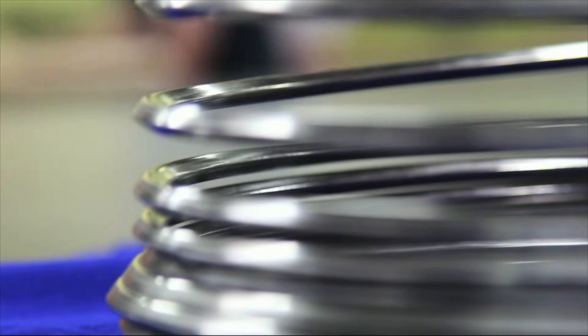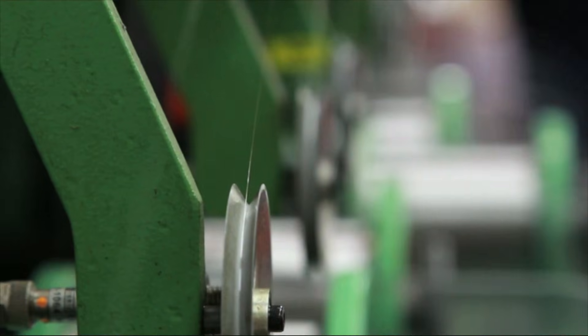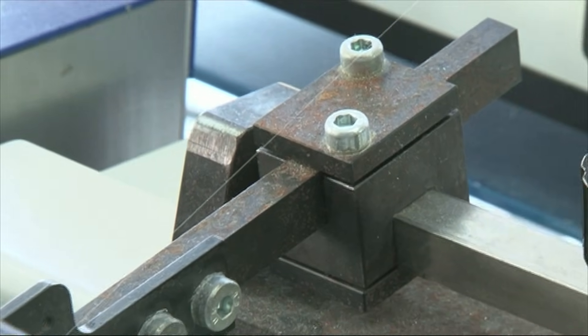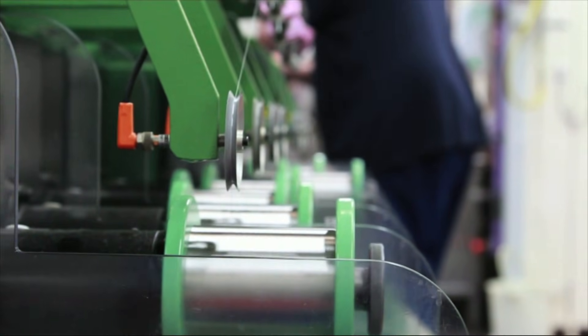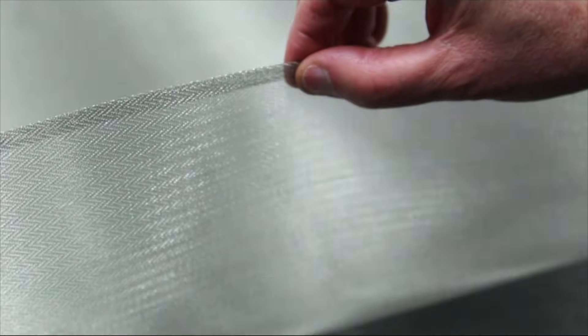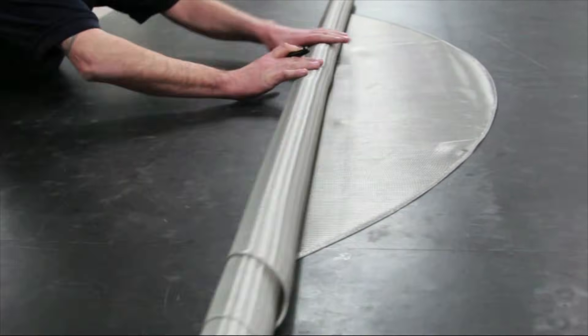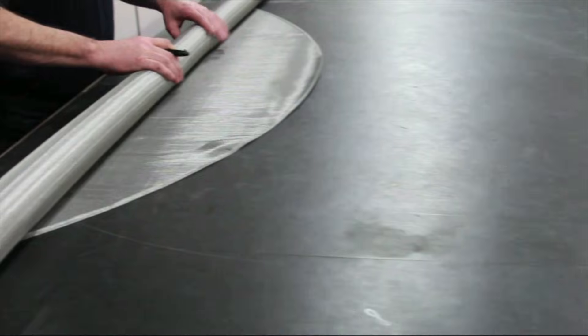They take this heavier bar and put it through a series of dies, till in some processes it gets narrower than a hair. I didn't actually take out a hair to measure, but I believed them — and I couldn't see it easily, though Brady is much better with his lens and saw it. Once they've got these fibers, these wires, they can then start making all sorts of materials. They can knit the fibers together or weave them, just like you do with cloth, to make fine meshes, which are used in the chemical industry for catalyzing reactions.